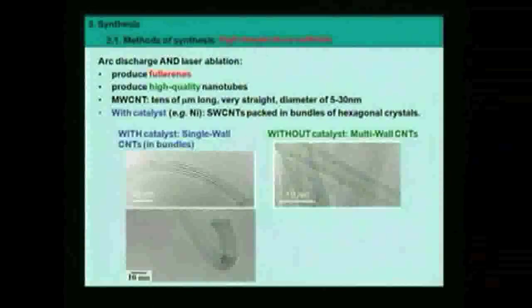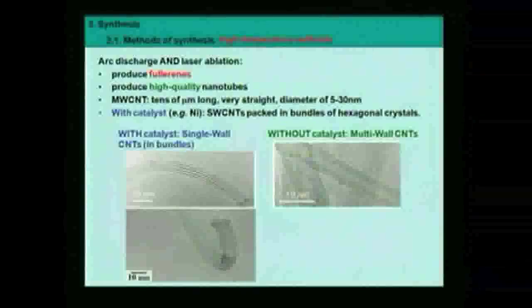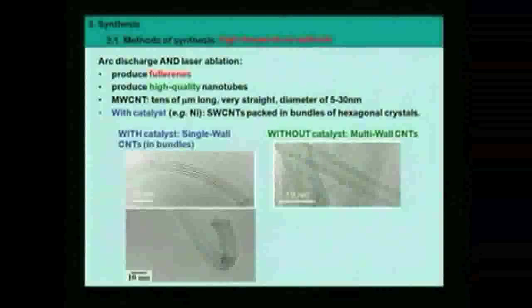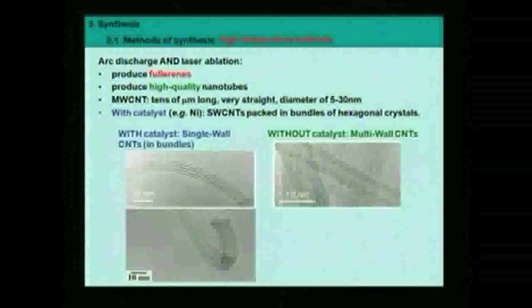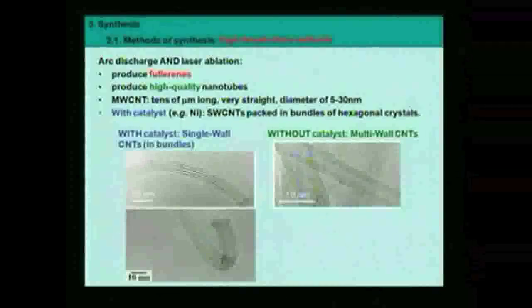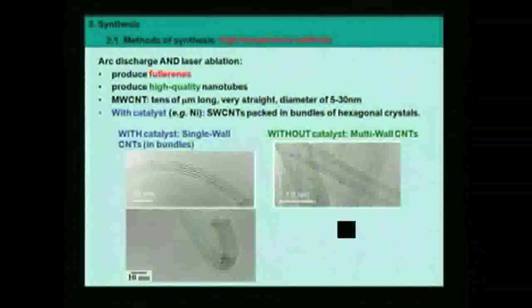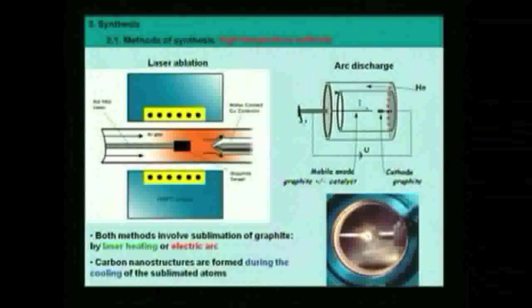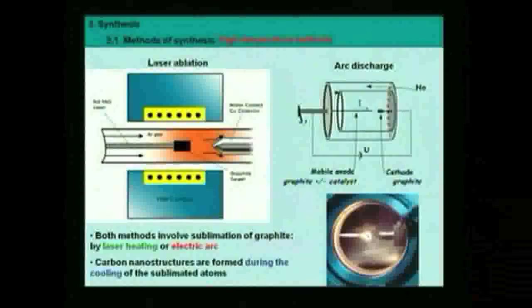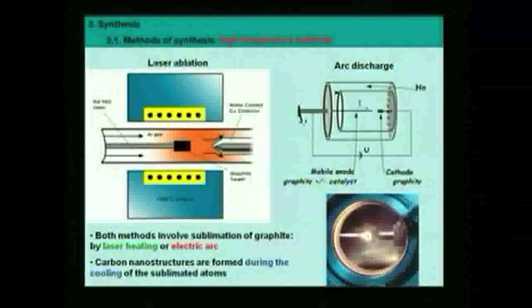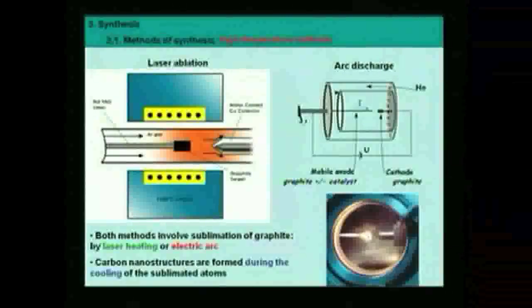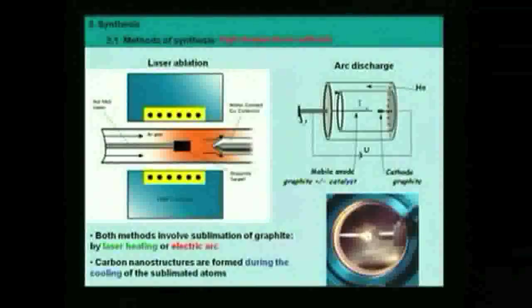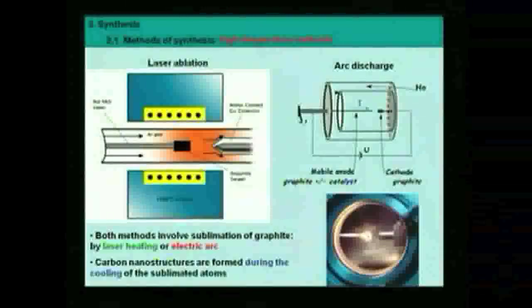Okay? And the second question was which technique is the best, arc discharge or laser ablation? The fact is that laser ablation was the initial technique, but it's very costly. It's very expensive. You need a very expensive laser to induce such sublimation. You need very special apparatus. On the contrary, arc discharge is really easy to make, and it's very cheap, and you don't need this special laser. So this is a much more democratic technique, but let's say that there are more byproducts, carbon byproducts, like amorphous types of carbon. Here it's more controlled, but very expensive. Here it's more democratic, but more contamination.